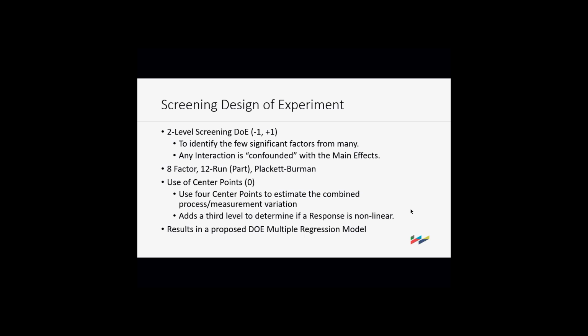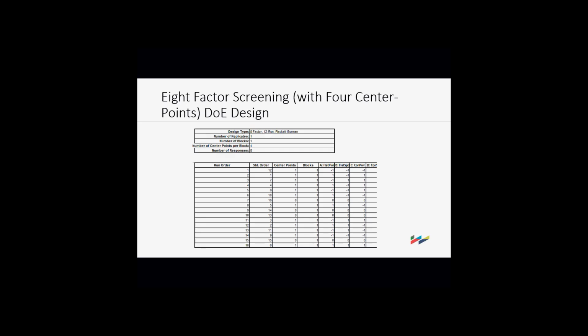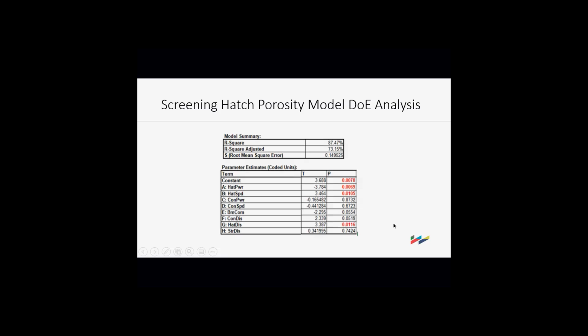And then we put that into a multiple regression model. A little hard to read, but here's the sense. I've got 12 runs that are involved with the factors, Plackett-Burman, and then I have the 4 center points. These are all randomized, the order is randomized. So this just gives you a sense of the highs and lows. I showed 3 here, but there are actually 8 in the table. With this one, for hatch porosity, R squared was 87%, R squared adjusted, pretty good, 73%. But what it shows here is, if the constant is below 5%, or 0.05, it says your model is not going through zero, that is, it's not your y-intercept, is basically what it's saying. But hatch power, hatch speed, and then hatch distance. So let me describe that a little bit.